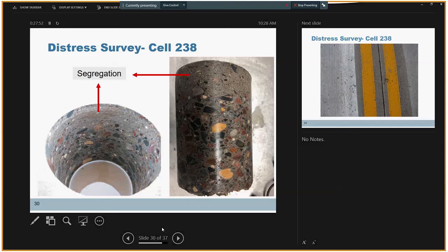But this is an image of the place that we had the main distress. You can clearly see that in the top part of the concrete, there is actually no coarse aggregate to restrain the shrinkage and to control the deformation. So that led into cracking.